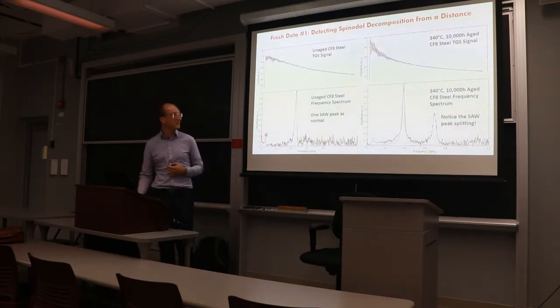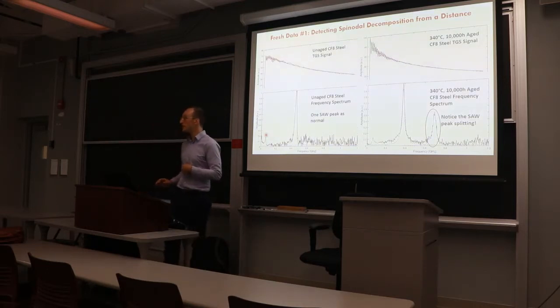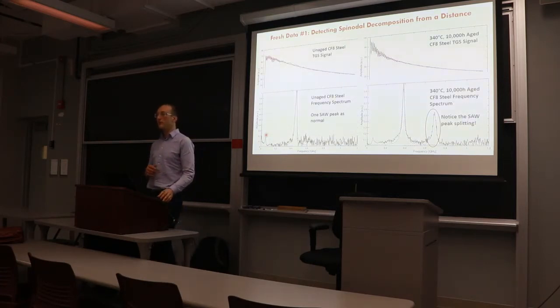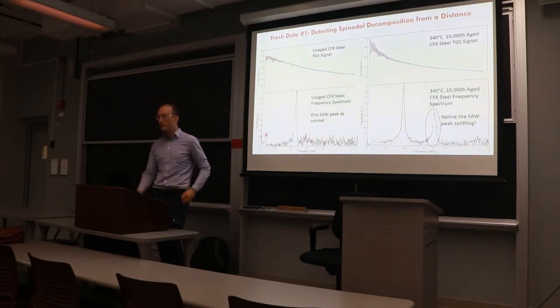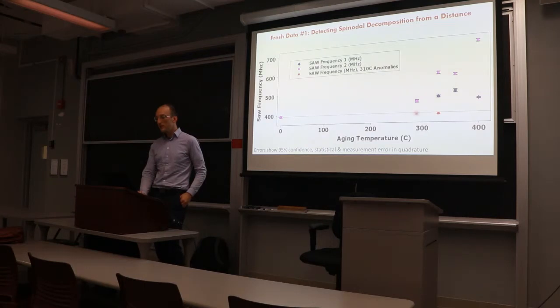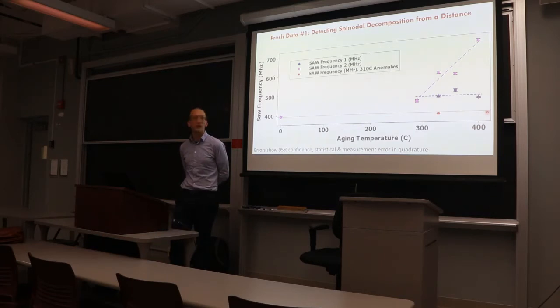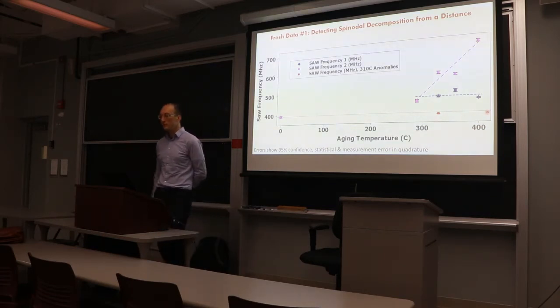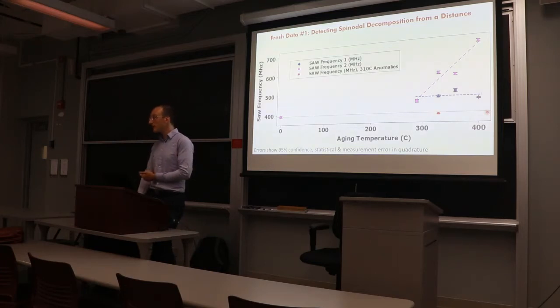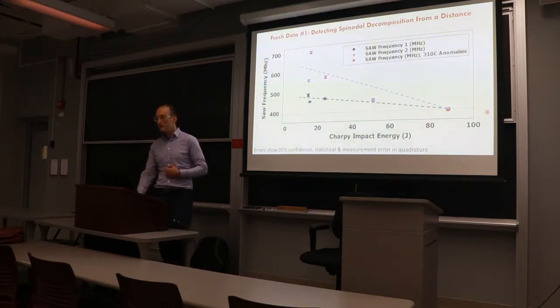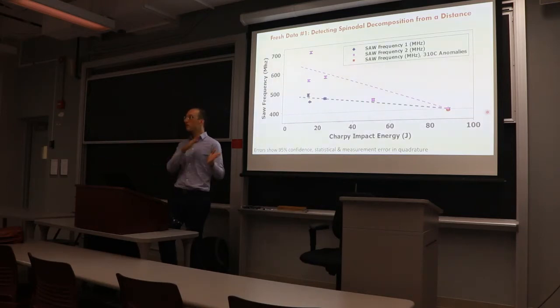And our going hypothesis is that peak is due to spinodal decomposition causing stiffening, which we're able to measure on our Vickers hardness indenter. This is another reason I wanted to talk to Professor Hostman, to understand this with nano indentation. But just from a correlation point of view, if we plot those first and second surface acoustic wave frequencies with temperature, we see that there's not much of a change for that first acoustic wave mode, but the second one increases fairly linearly, with our very few data points, with aging temperature. And to replot this with the value that people actually care about, Charpy impact energy, the surface acoustic wave speed, let's say they increase at different rates.